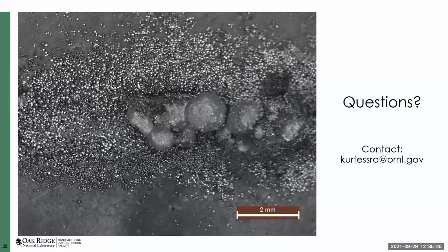So one of the things I'm looking at is the laser affected area. I didn't include it because I haven't finished all of the samples yet, but I'm cross-sectioning these samples and looking at the YZ plane of each section, determining how much of the polymer is degraded by the laser. So you get basically a channel that no longer has polymer in it, and also the laser affected area, an area in the polymer that looks like it has been melted and re-solidified. What we're looking for is less laser affected area and smaller channels. We want to stay as true to the original geometry of the polymer as possible.